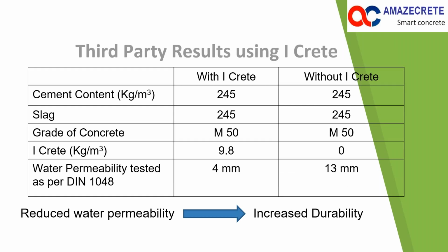Yes, so here again it is a classical example where the permeability is reduced in a very big way by usage of iCrete. At the same mix, when 2% of iCrete is used, the percolation of water as measured as per DIN 1048 has reduced from 13 mm to 4 mm, which is a tremendous reduction in the permeability, leading to increased durability. Next one.